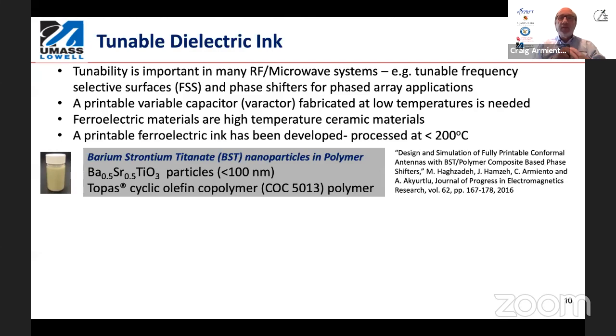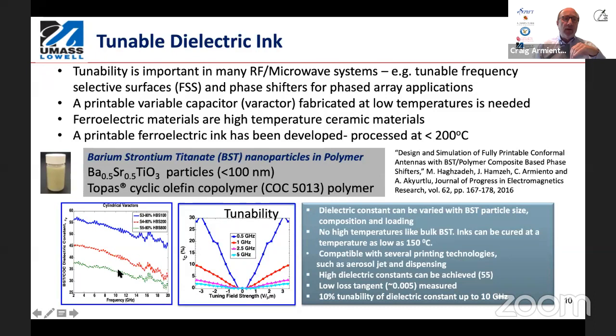I mentioned earlier some of the novel materials we've developed. In many RF applications, tunability is important for frequency agility. You'd like to have a varactor or some tunable element, a variable capacitor. And we developed an ink that's based on a well-known ferroelectric ceramic, barium strontium titanate, or BST, and came up with various formulations of those nanoparticles in an ink. What you can see here is that by modifying the formulation, the particle size, the concentration, and so on, we can formulate this ink with different dielectric constants.